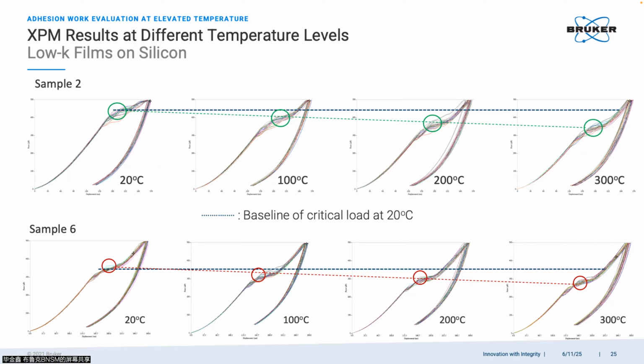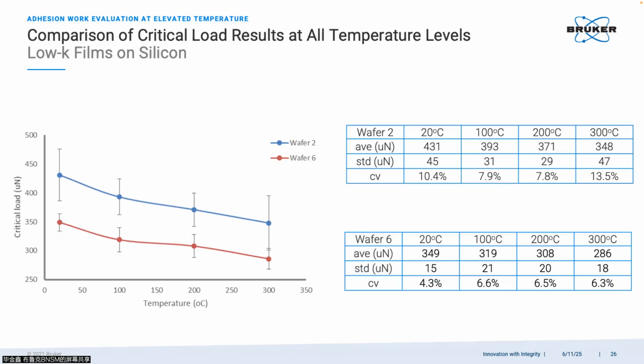So this is the very first example I'd like to share with you. You can see we have wafer 2 and the other one, wafer 6. Their interfacial bonding is different, and we can perform an indentation array to induce debonding locally, position by position, and then we can control the temperature. So this is room temperature, and 100 degrees Celsius, 200, 300 degrees Celsius. You can see that obviously your critical force, which is the force required to delaminate the interface, decreases when the temperature goes up. That means your interface is getting weaker at higher temperature. A similar behavior can be found in the other wafer, and we can get the critical load results changing with temperature.